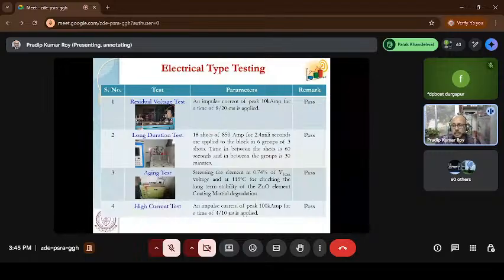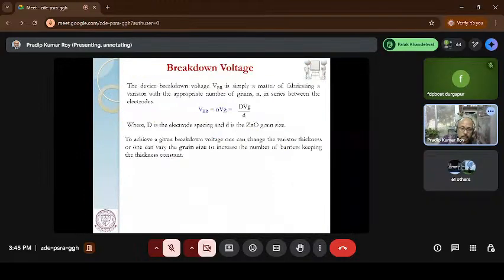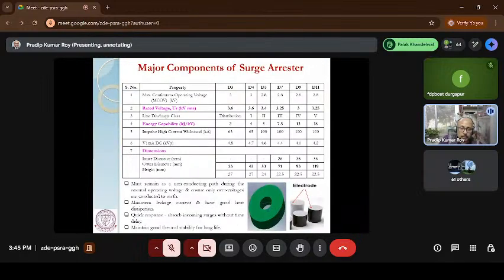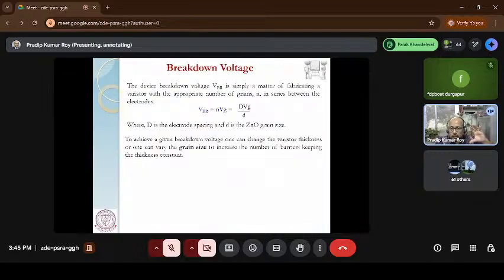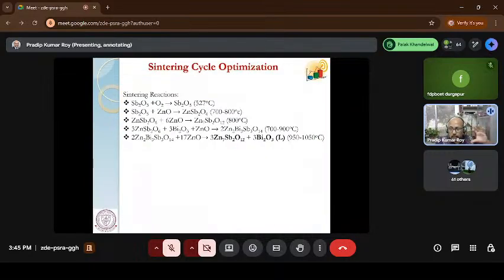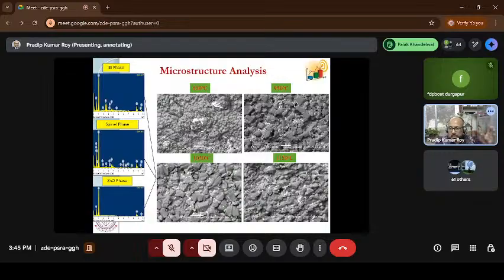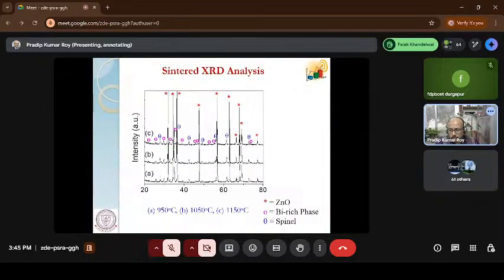And for a long duration test, normally how much energy handling capability should the block have? If you remember the slide, for example, this D3 block, the energy handling capability is 2. So if I take 30 blocks together, the energy handling capability is 60 kilojoule per kilovolt. Based on that, my surge voltage should not be more than 60. Otherwise, it will break that surge arrestor.